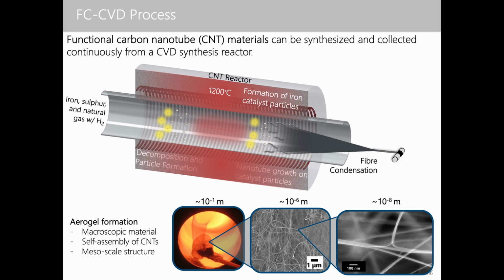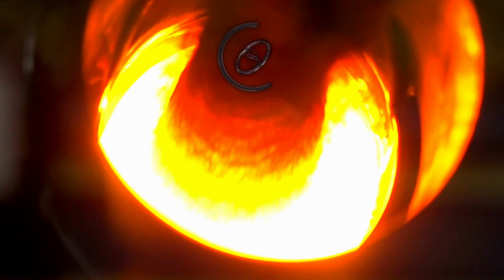And then the nanotubes ultimately grow from the catalysts that form, the iron and the sulfur form a catalyst that grows the nanotubes. And what fascinated me about this process is the nanotubes then self-assemble and make a macroscopic material that one can just pull out of the reactor. It looks like a black candy floss, something you wouldn't want to feed your kids, but nonetheless is this emergent property that we still can't fully explain mathematically, but it's fascinating to me nonetheless.